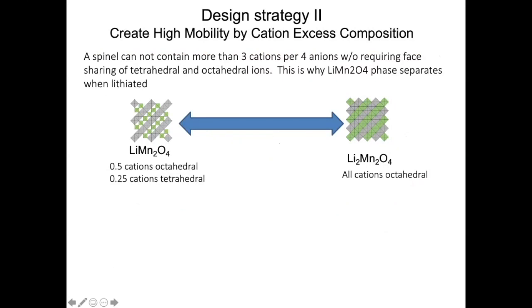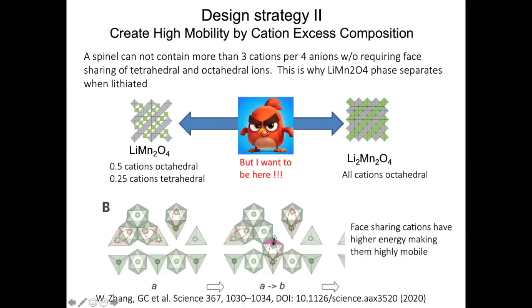Strategy two was much harder. What I really would like to make is a compound in between these two end members. And again, the problem is that in reality, they phase separate. What does phase separation mean? That you cannot make something there because it will phase separate into spinel and the lithiated spinel. Now, we want to be cation excess. You want to have more than 3 cations per 4 anions.